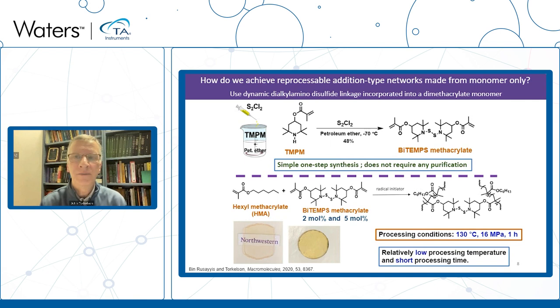That work was a case where we were doing reactions of polymer and monomer in making these particular materials. We also have approaches where this can work if you're just making the networks from monomer, with that reaction actually producing the network, and then showing that that network can be reprocessed. So here we use an approach where we use dialkyl amino disulfide bonds, and I'm using my arrow here to draw a circle around those. Those linkages actually have very good dynamic character, where they will dissociate again at elevated temperature, but be very robust bonds at lower temperature in these particular cases.